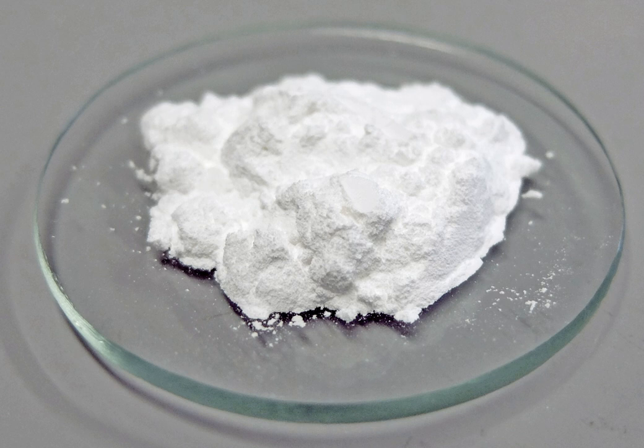The addition of the La2O3 to the glass melt leads to a higher glass transition temperature from 658 degrees Celsius to 679 degrees Celsius. The addition also leads to a higher density, microhardness, and refractive index of the glass.